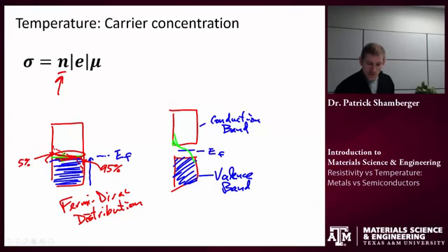And the greater the temperature is, the greater the number of free carriers I'm going to have. Now remember, our semiconductors tend to be carrier starved. So increasing that number of free carriers has a very large impact on semiconductors, as opposed to the metal case.